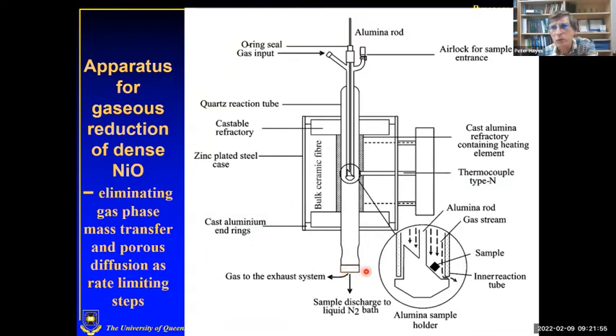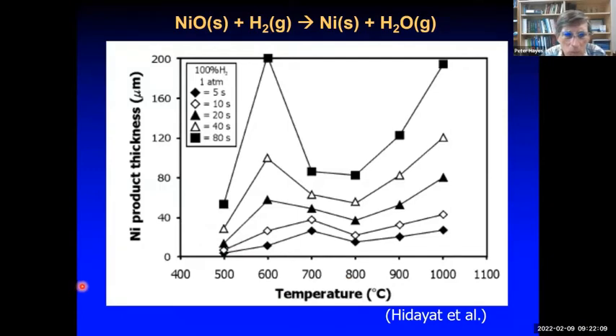Normally, as pyrometallurgists, we don't have this luxury. Things are inside a big furnace and we can't get inside to observe. But this apparatus allows us to do that by stopping the reaction through quenching it. And we can measure the thickness of the product produced at different temperatures. So these are isothermal tests done at different times. The diamonds at the bottom are giving us only 5 seconds, whereas the squares at the top, that's 80 seconds. So you can see as time goes on, the thickness gets larger for any particular temperature.